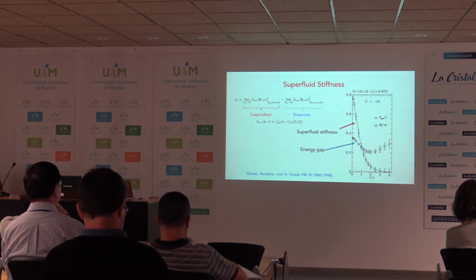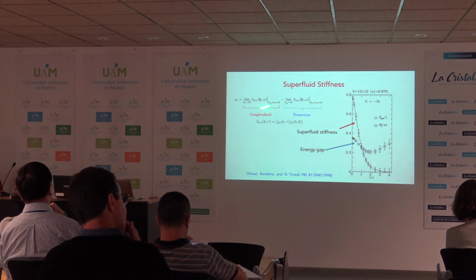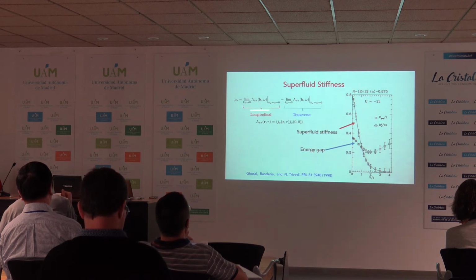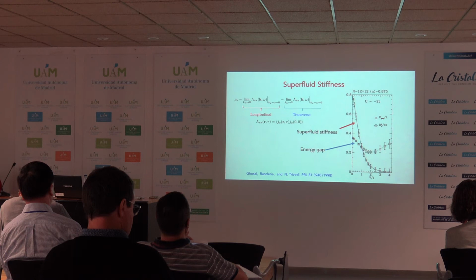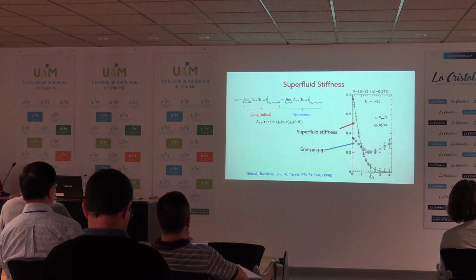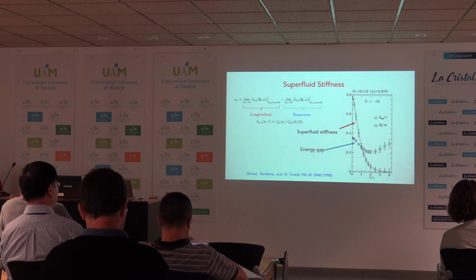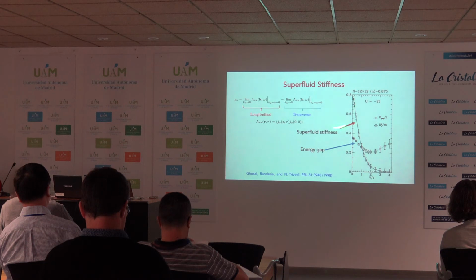So here are some more results showing now how we calculate different things. For example, the superfluid stiffness is obtained by a current-current correlator, and what you have is sort of like your helium experiment, where if you want to measure the superfluidity, you try to take your liquid in a pipe and push on it longitudinally, and that gives you the total density. And if you now try to shear it, only the normal part contributes. So that's a different limit of this current correlator. From the difference, rho minus rho n, you can extract the superfluid density.